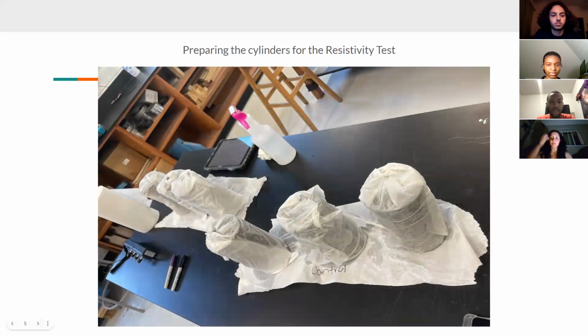And here is a picture of us preparing the cylinders for the resistivity test. As you can see in the picture, we wrap the cylinders in damp paper towels in order to keep the surface more moist before starting the test.